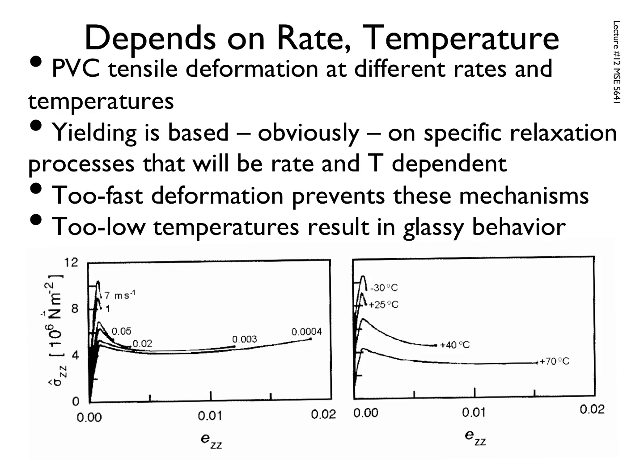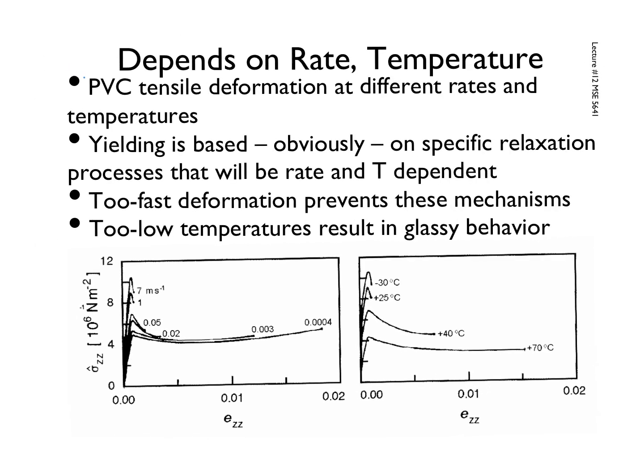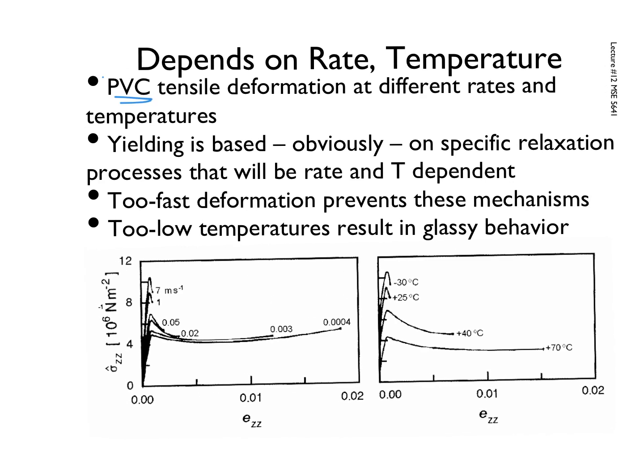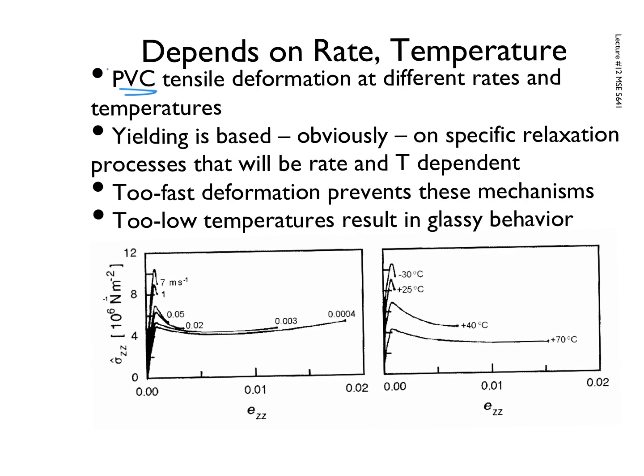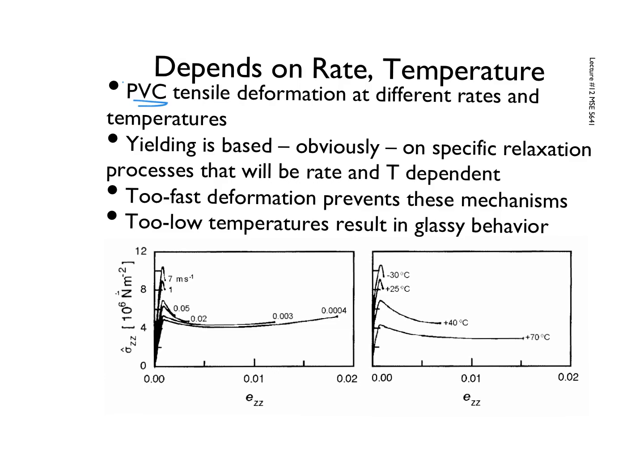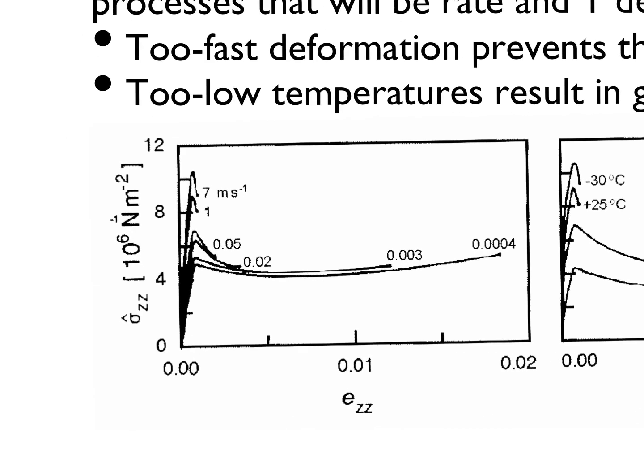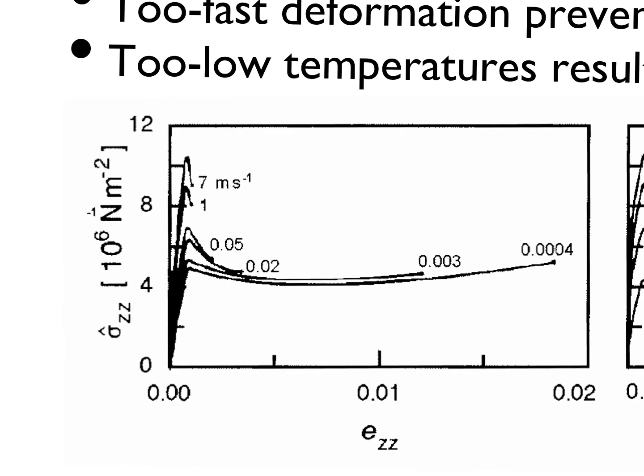And then this depends very strongly, as I mentioned, on rate and temperature. This is a good example of PVC. And again, we're talking about not the PVC that you can buy at Home Depot, because that's full of plasticizer. This is pure PVC, although it also is significant for the pipe you buy at Home Depot, as we'll discuss in a second. Tensile deformation at different rates and temperatures. So let's just dive right into the data here. We're looking at the stress strain behavior of a piece of PVC at strain rates of 0.0004 meters per second all the way up to 7 meters per second, which I looked up, it's about 16 miles an hour. So pretty fast.